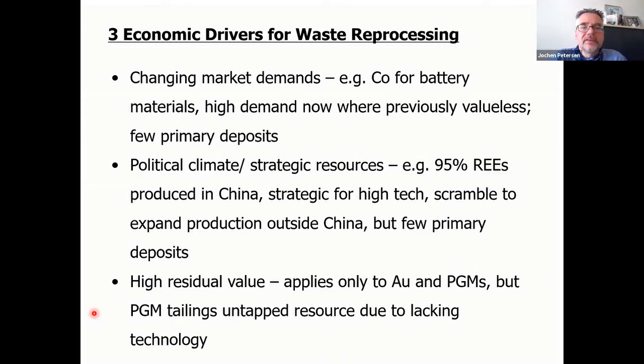So there are three economic drivers for the reprocessing of waste. The one, and I already alluded to that, is changing market demands. Cobalt for battery materials is the classic example because it was almost considered valueless previously, and in the last 20 years or so, suddenly demand has skyrocketed because there are very few primary deposits of cobalt, actually none. Cobalt is always mined together with copper. And so where it was previously separated away from the copper phase, it is now co-treated and co-extracted. But historically, there are significant amounts of tailings still available that contain extractable or economically attractive portions of cobalt.